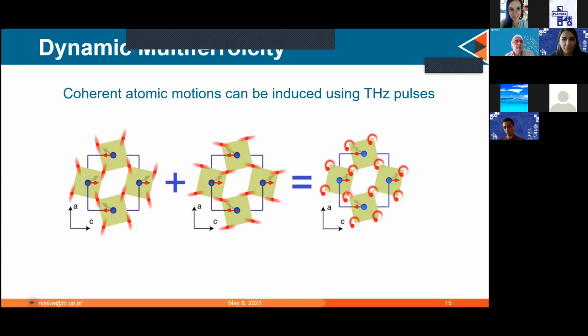And as you know, if you have a circular motion of atoms which are actually ions, so they have an electric charge, you create local currents, local spins. So you can generate magnetism from this. So at the same time, you can use one or the other and induce ferroelectricity or ferromagnetism in paramagnetic and paraelectric material, virtually in any kind of materials, and have dynamic multiferroicity for some picoseconds.